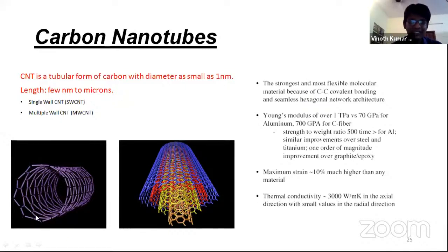These are of two types. One is single walled carbon nanotubes, and another one is multi-walled nanotubes. And these are the strongest and most flexible molecular material, having high mechanical strength. The Young's modulus is over 1 terapascal, compared to 70 gigapascal for aluminum, which is better than aluminum. And this has a maximum strain of 10%, and thermal conductivity is around 3000 watts per meter kelvin.